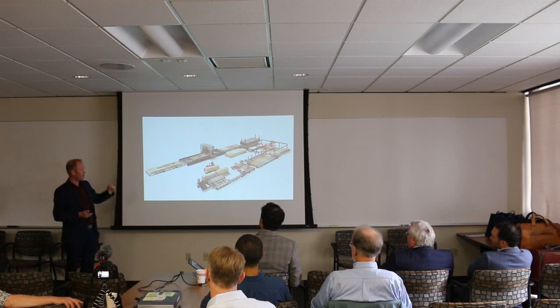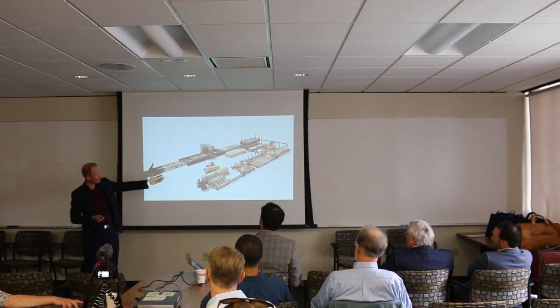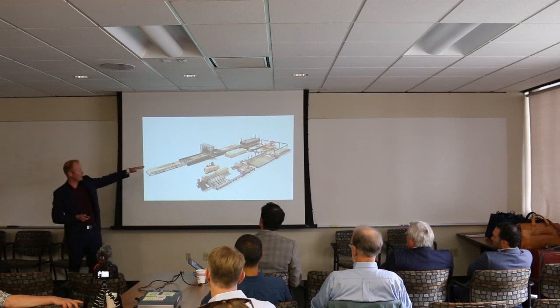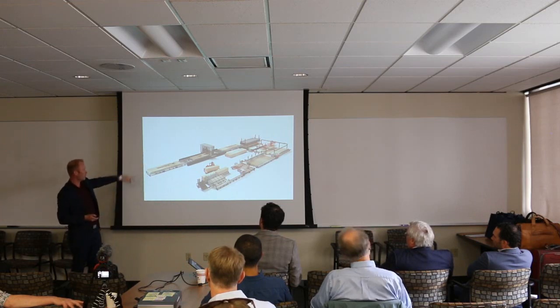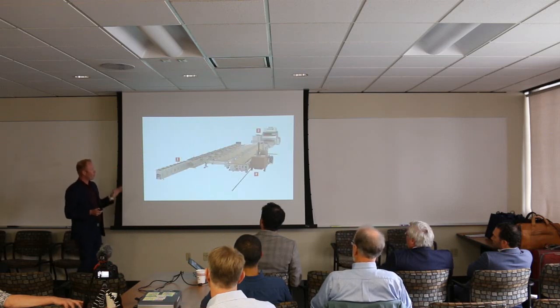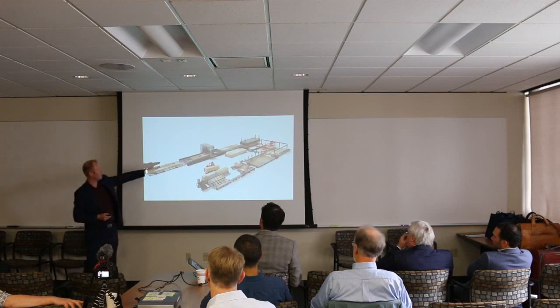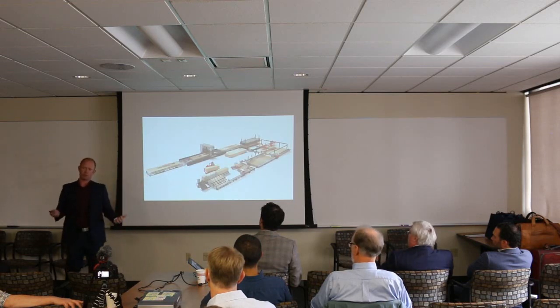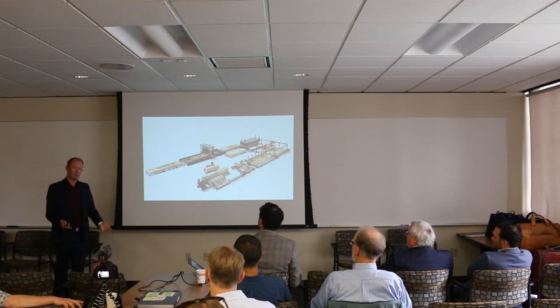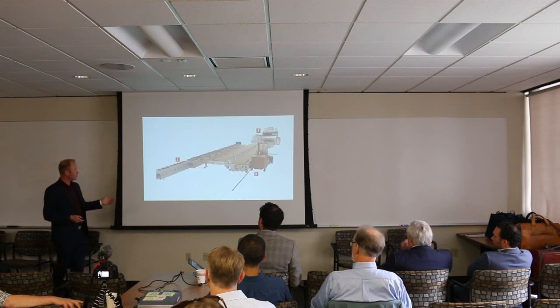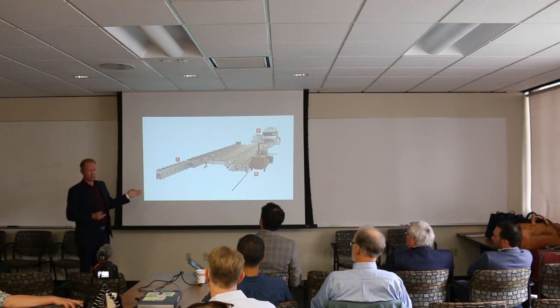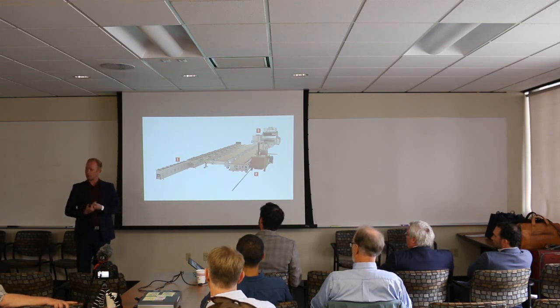So this is a diagram, I believe Minda put this together. And this just shows, you take lumber, you finger join it together, you make it long, then you lay it up, you glue it, you press it. As it comes through, then you cut out the doors and window frames. We're going to use a different technology to where we do this part ahead of that. So we're going to press it with the doors and windows already roughed out. The reason is the value of the raw material is about 50% of the cost. So why would we be cutting the blocks out and then have a non-usable block? So we've discovered that there's a company in Europe producing a press line that will allow us to do glulam beams and CLT in the same press line using radio frequency technology to cure the adhesive at a high rate of speed.